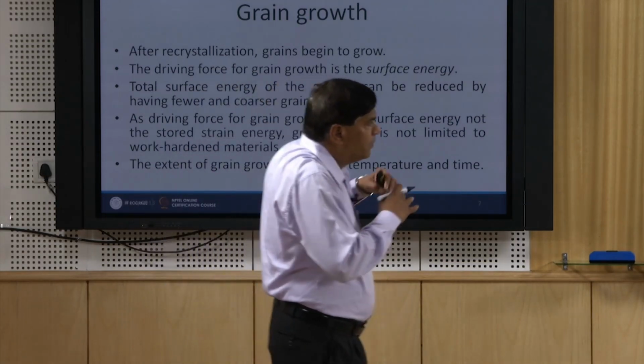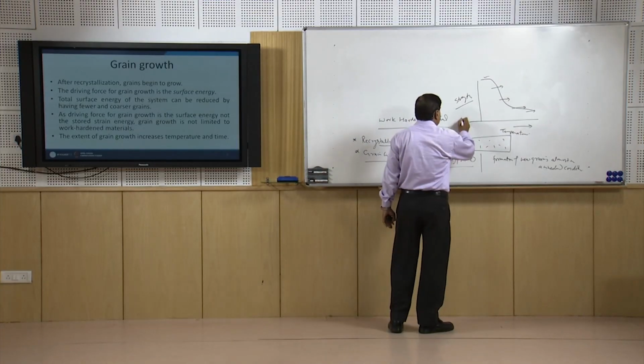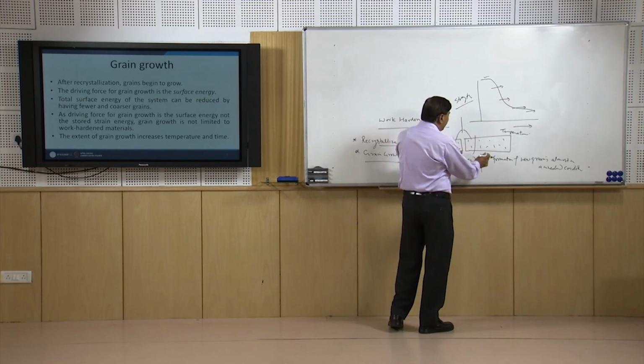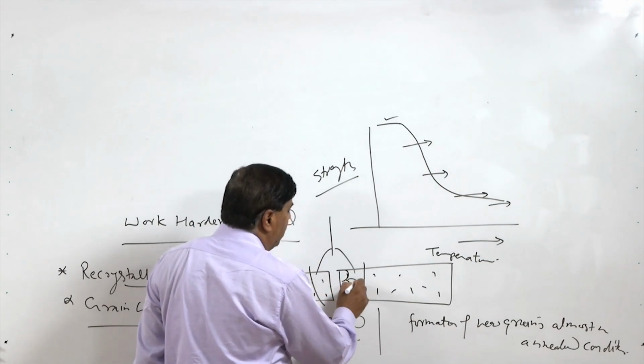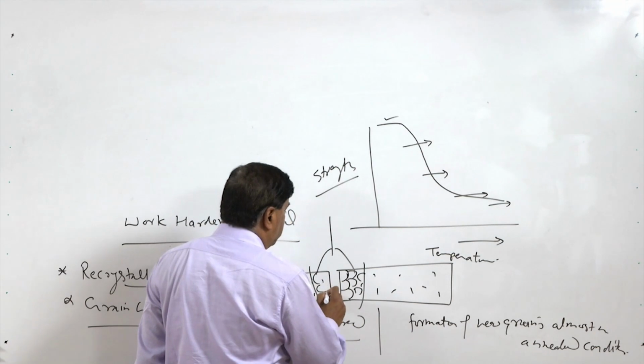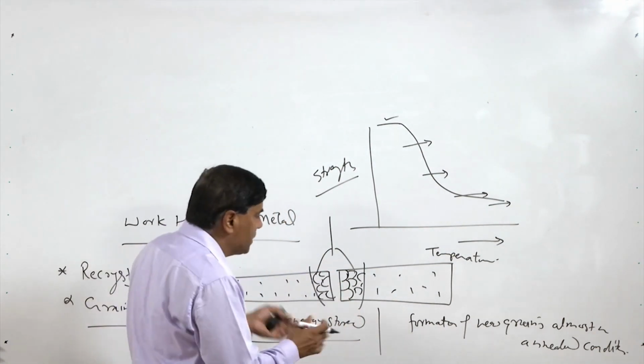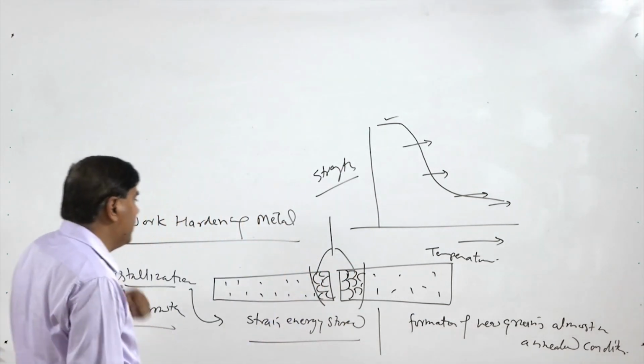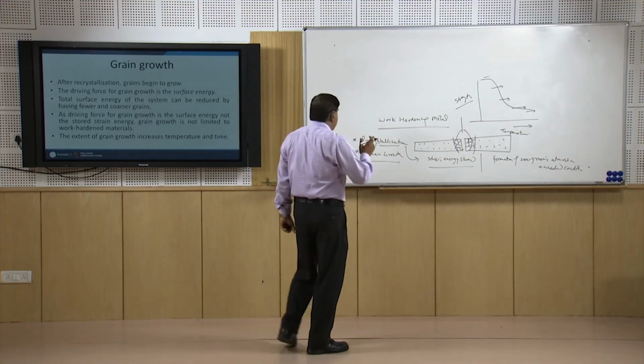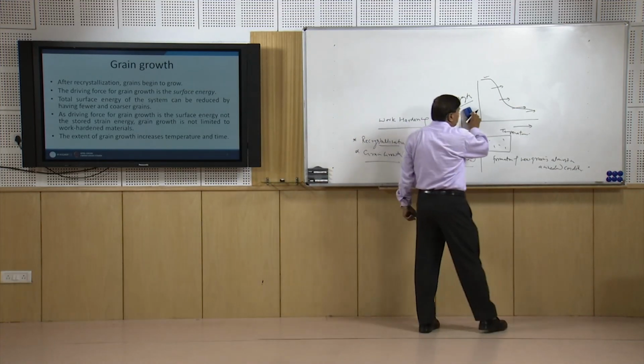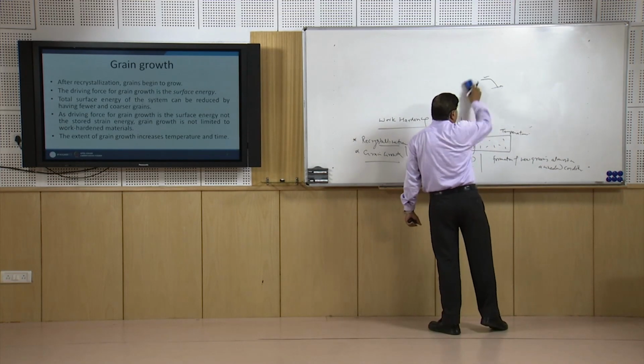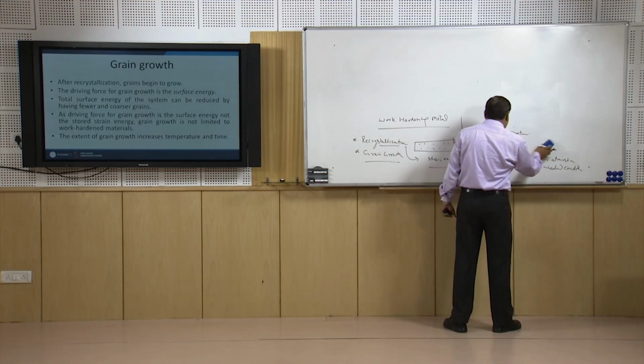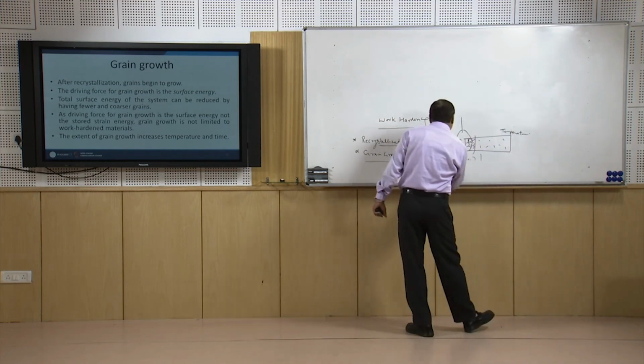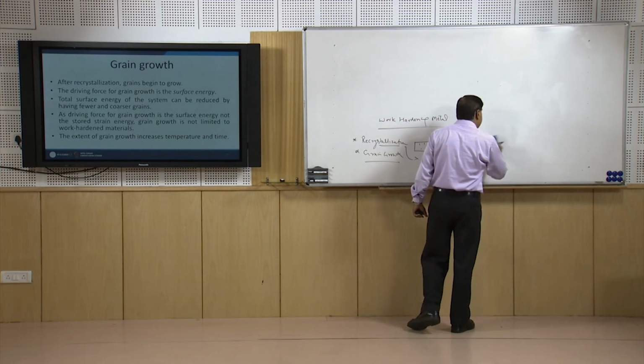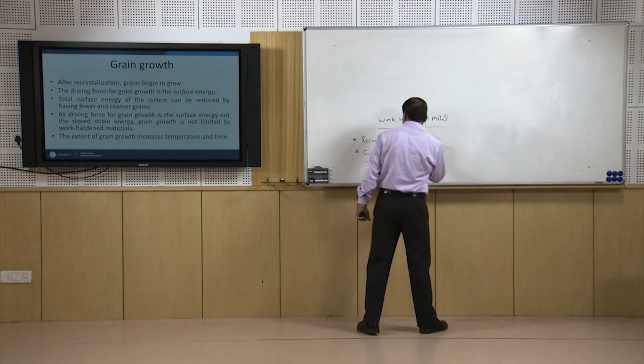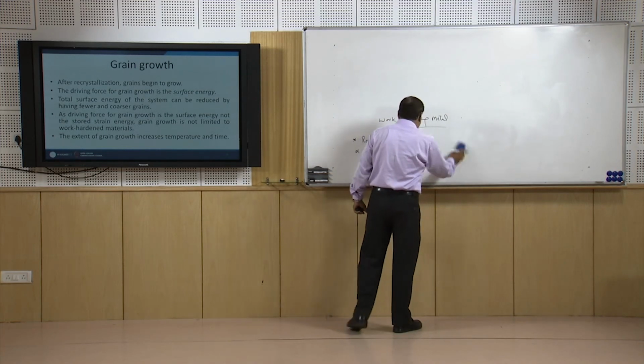This is what we can see: whenever the work hardened metal system is exposed to external heat, the metal near the heat affected zone recrystallizes, and the formation of new annealed grains lowers the strength of the metal as compared to that of the work hardened condition. So, basically the effect of work hardening is lost due to recrystallization, and if the application of heat and high temperature exposure is continued, it will cause the growth of the grains. Growth of the grains again causes a reduction in strength and hardness because of grain coarsening. The driving force for grain coarsening is different from recrystallization. So, that is what we will see now, the factors governing the grain growth.